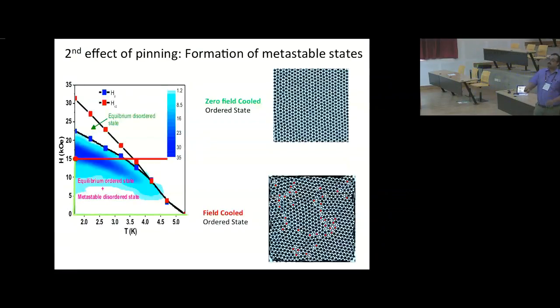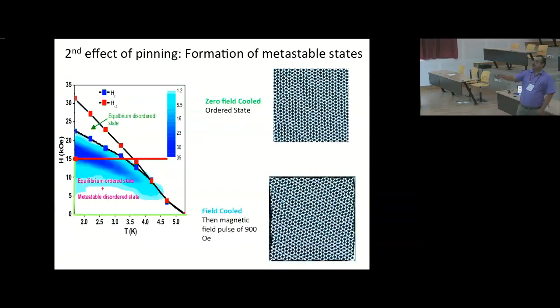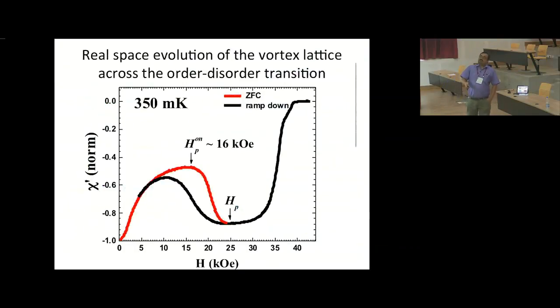For that, I shake the vortex lattice by applying a magnetic field pulse. When I shake it here, nothing happens. When I shake it here, it transforms into something that is identical to this. So I know that this zero field cooled state is the equilibrium state of the system. So this is important, and we will be using this scheme of pulsing in subsequent measurements. All right. So now let me come to the real data.